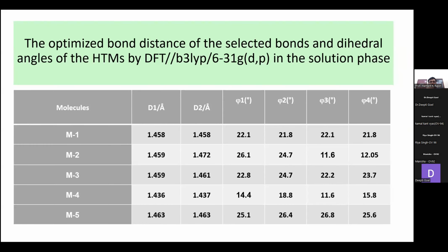Moving towards their distances, the distance between the linker and basically the donor and the acceptor. So we look at the symmetry here. The more symmetry there is in the structure, the more it is able to pass the electron and hole as compared to a puckered structure. So a puckered structure is not that much of use. Basically all of these are fine, but if we look at M2 and M3, there we can see a slight difference in the bond length. If we talk about the angle as well, for M2 we can see a slight variation between the two sides of the donor.